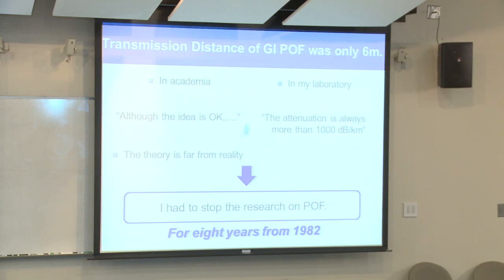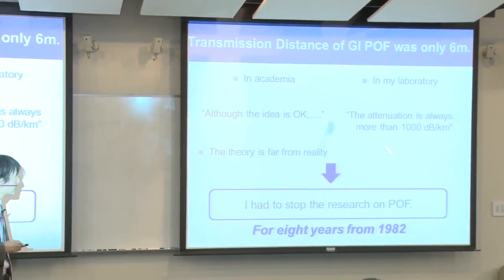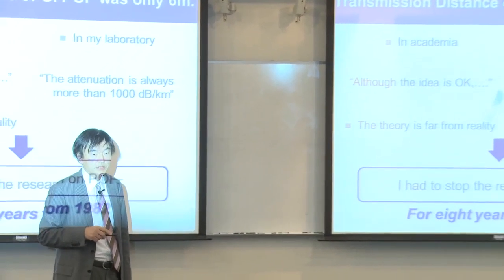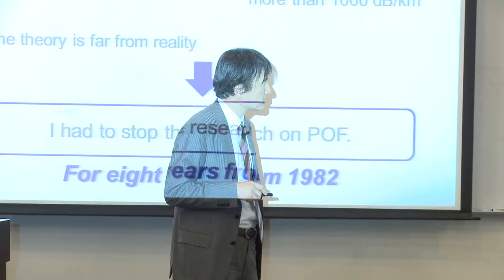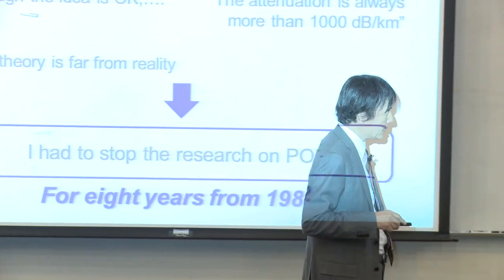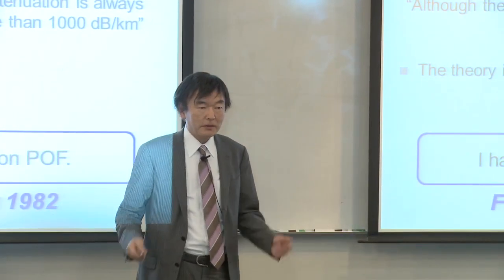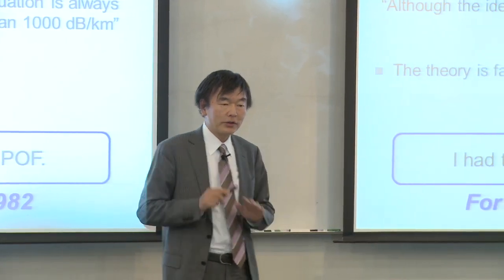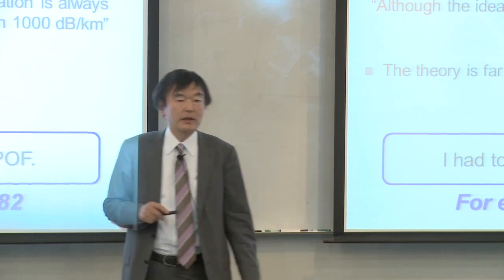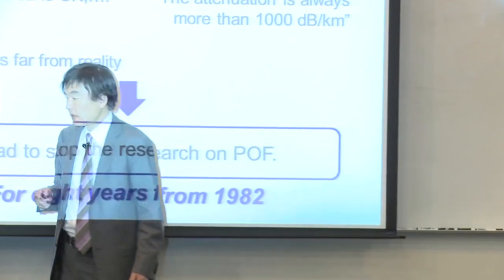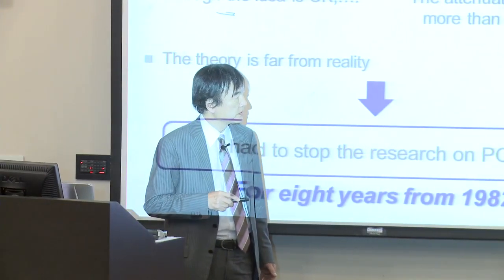At that time, I was still single. And I very often made fiber overnight, and the next morning, the fiber loss was always more than 1,000 dB per kilometer. And so, finally, I was obliged to stop the research on the POF from 1982. After 1982, when I received the PhD, my research career was very smooth, but right after I received the PhD, I met the first slump. There's no reason. I don't know. What is a way to break through?